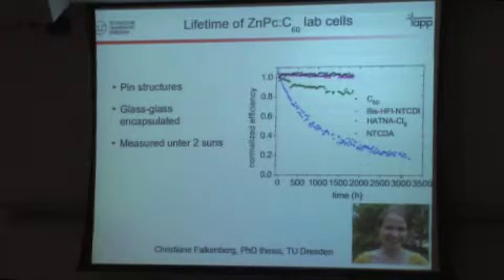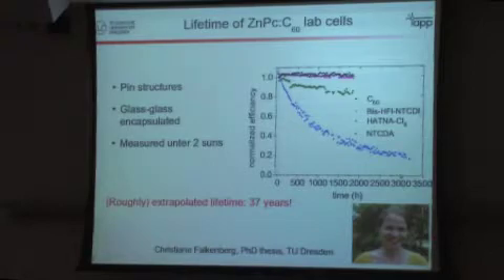She found some materials which can replace C60 in terms of efficiency, but when she did the lifetime measurement, unfortunately and disappointingly, the C60 still gave the best lifetime results. And she was measuring this under an intensity of 2 suns. We used simple glass encapsulated devices. And stability is defined as a lifetime is a 20% decay. And when she did a very rough extrapolation for her thesis, it would have been, at least under German conditions, it would have been a lifetime outdoors of 37 years.